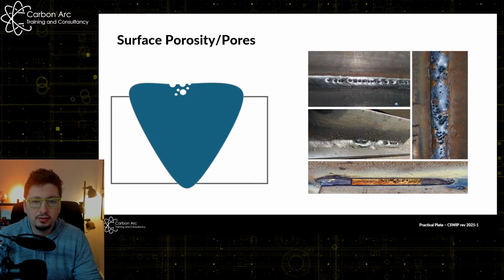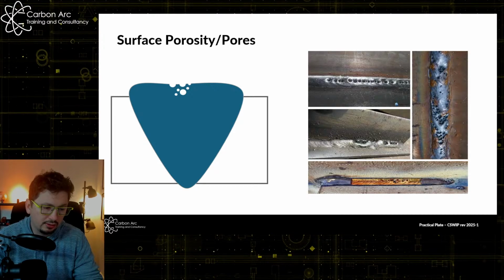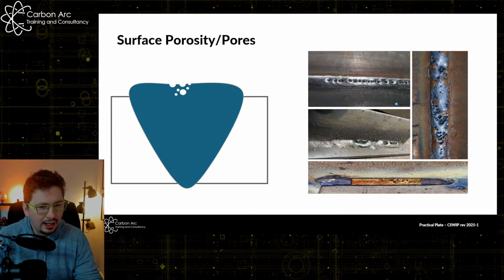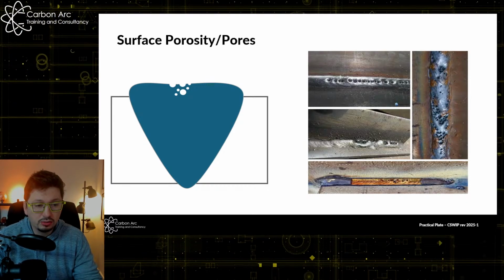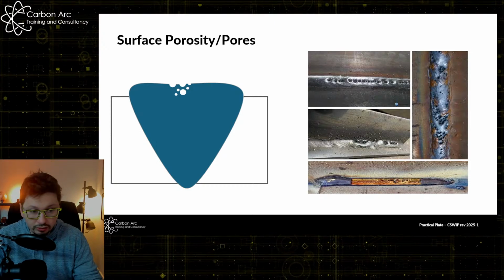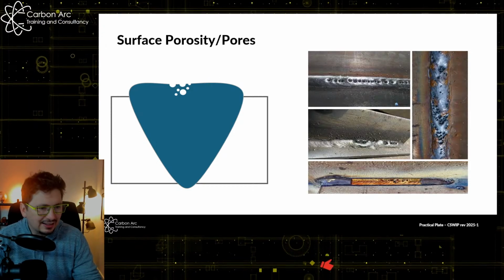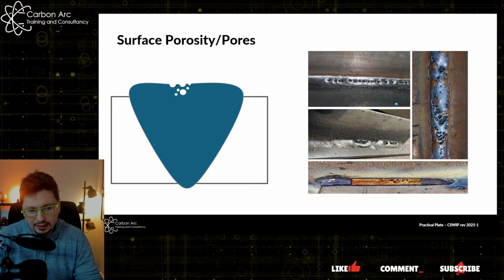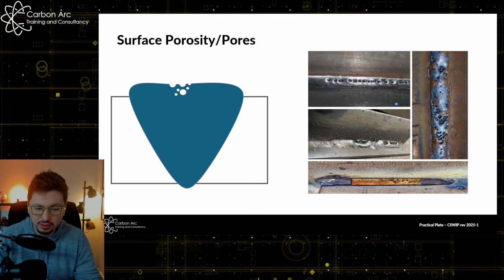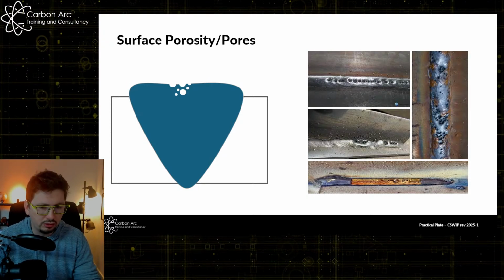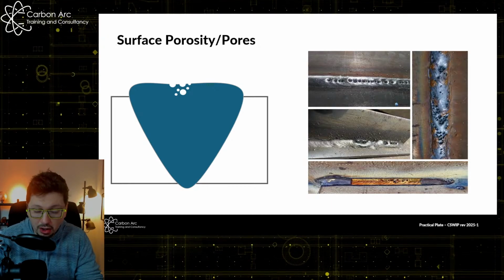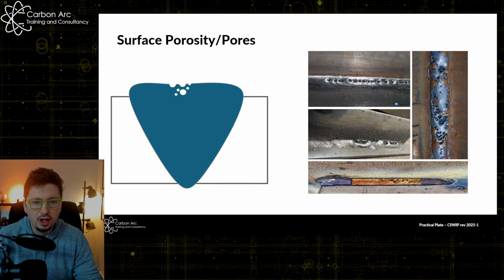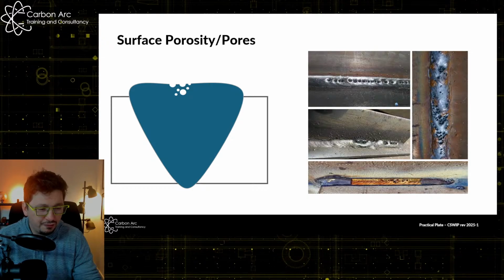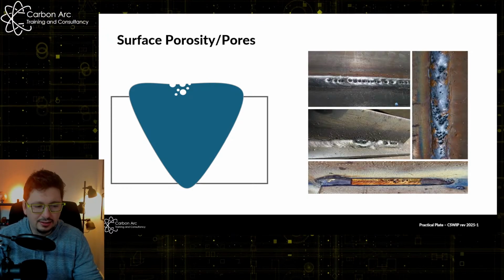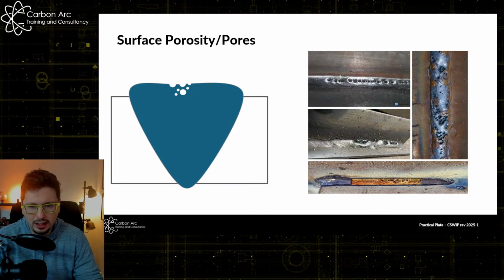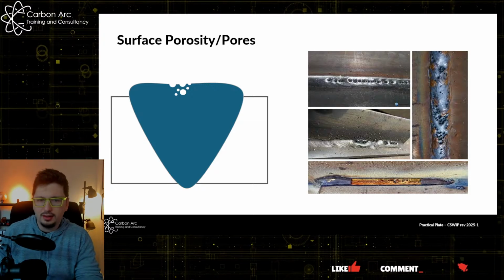So generally porosity is occurring along on the stop starts of the welds. If you've got an MMA weld and it's maybe lost a little bit of its flux when you start up, or you've had a lot of loss of gas in either TIG or MIG-MAG, that's likely where it's going to be. And the hope is that the welder starts, realizes there's no gas, and stops, and doesn't continue on like the weld we've got up on the screen here. Okay. Sometimes it's a little bit harder to see if you've got flux core welding or something like that, where the weld might be covering up, but you can generally have a feel of it, right? And you can see it occurring as you weld them, so hopefully it gets there, right?